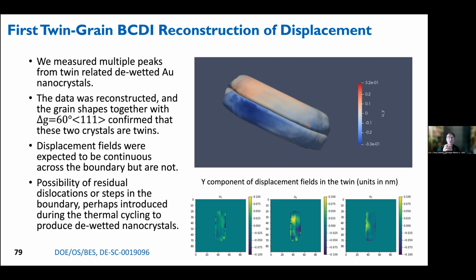You also know that if you are correct that those two crystals are in fact twin related, that misorientation is very precise. I mean, it really is 60 degrees plus or minus a tenth or less. Anyway, so what you see here is actually the first twin grain reconstruction, and actually coupling the two grains as well as coupling the multiple peaks from each one. And you do see a little bit of variation of displacement within the twin pair.